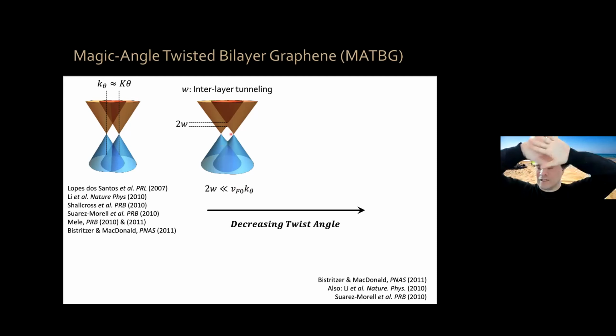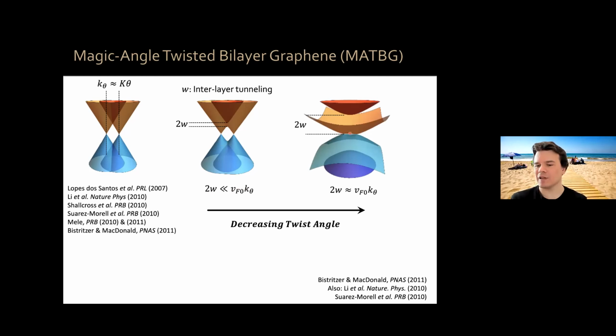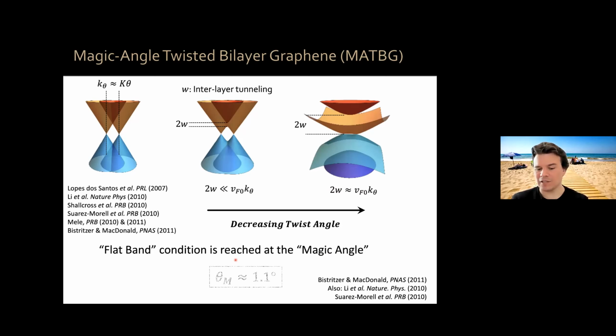But as you decrease the twist angle, these two Dirac points come closer and closer. At 0 degrees, they would be on top of each other. So this bonding band gets pushed down to lower and lower energies until it reaches 0. When the interlayer tunneling is of the same order as the energy of that crossing point, we say that a flat band condition has been reached. And that occurs at the magic angle, which was theoretically predicted to be 1.1 degrees for graphene on top of graphene. These were theoretical predictions by Bistritzer and MacDonald, who predicted these flat bands at this magic angle.